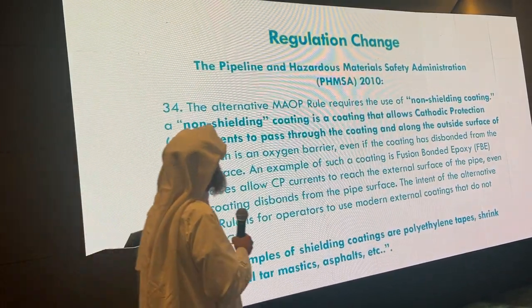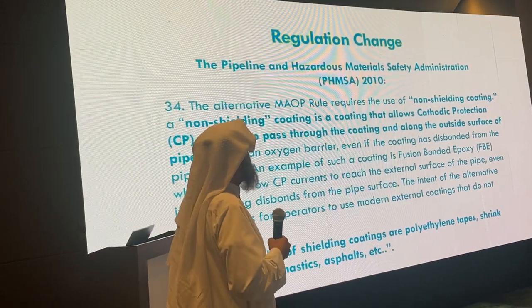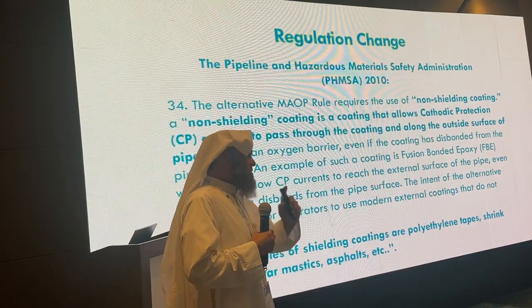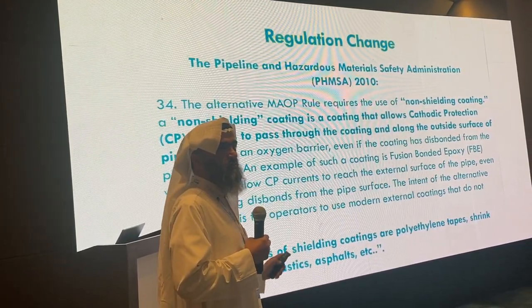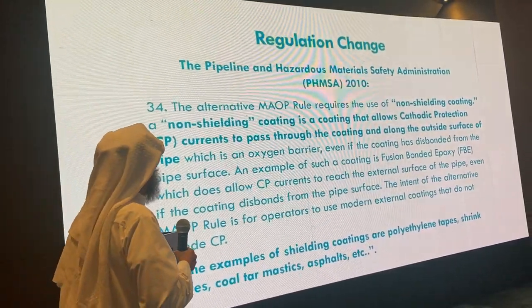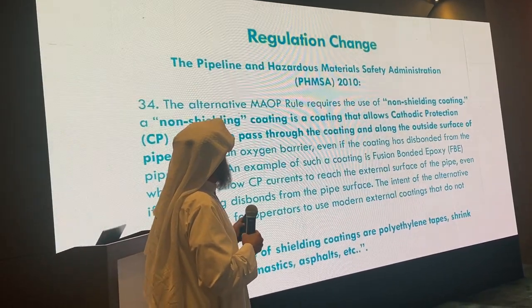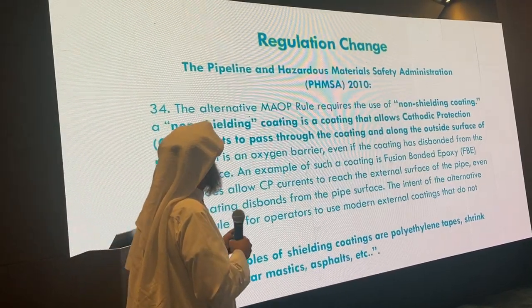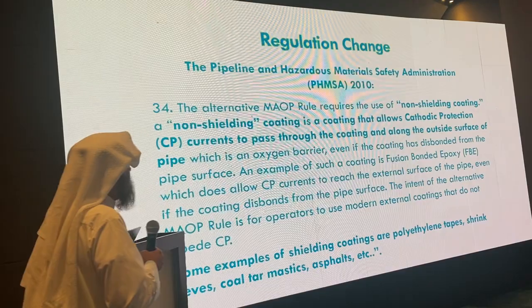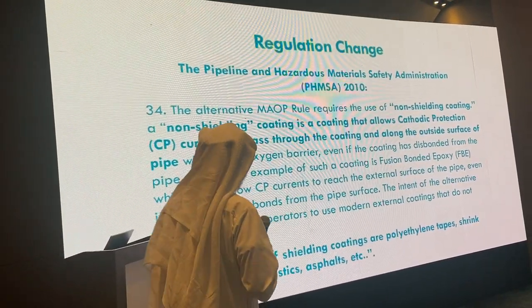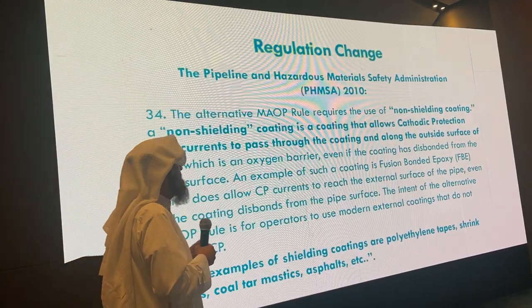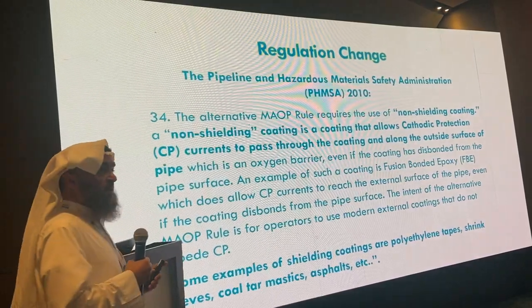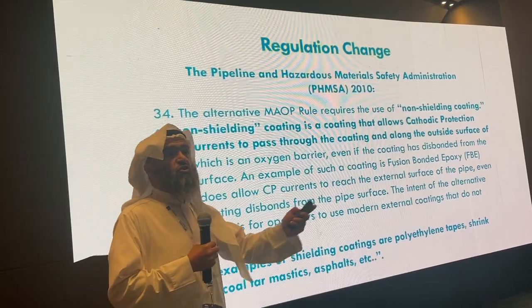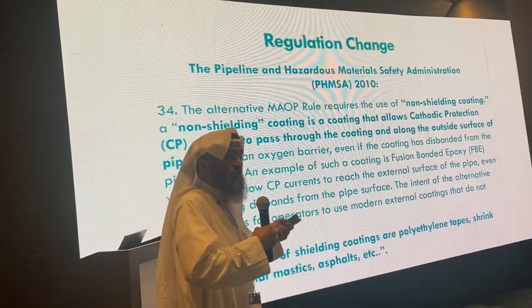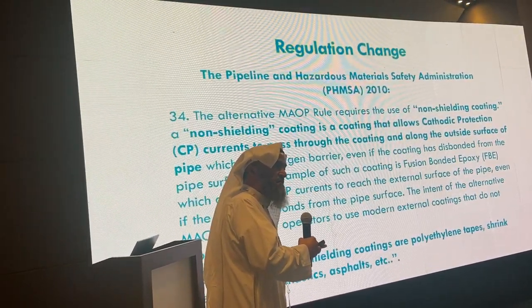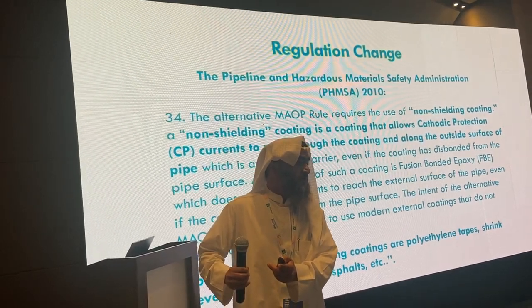Now, the Pipeline and Hazardous Materials Safety Administration, PHMSA, in 2010 put this rule which stopped all polyolefin tapes or heat shrink sleeves from being installed on pipelines in North America. The alternative maximum allowable operating pressure rule requires the use of non-shielding coating. A non-shielding coating allows cathodic protection current to pass through the coating and along the outside surface of the pipe, even if the coating has disbonded from the pipe surface. That means if the coating disbonds, the current should go through. You shouldn't put in a system with two defense lines where, if the first defense line fails, it prevents the second line from operating. And this is what's happening with polyolefin.